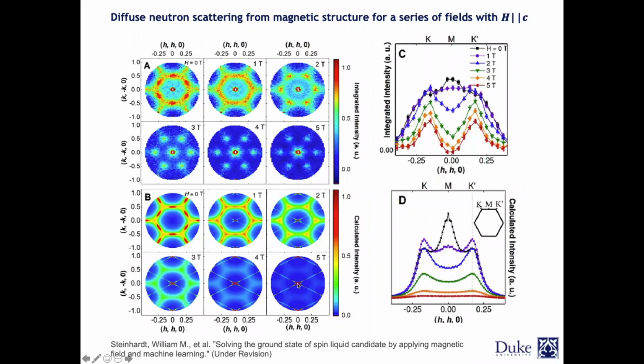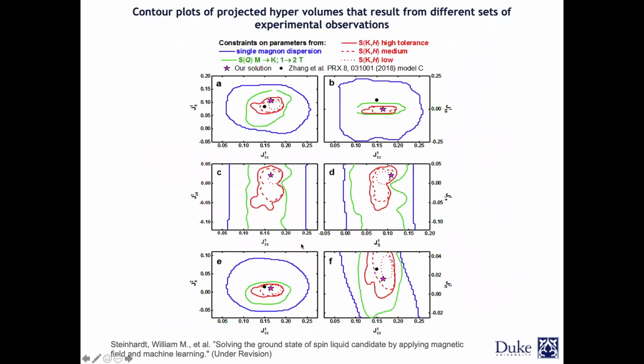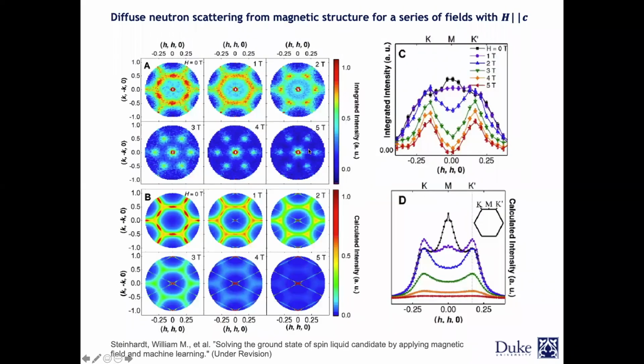Okay, so we decided to do some neutron experiments on this. The key was that we already know that from 0 Tesla to about 5 Tesla in our TDO data, something is happening. Let's go and figure out what is going on. Here, these are the experimental data. The energy is integrated all over, so it goes from almost 0 to about 2-3 meV. All the low energy excitations that are talked about are captured in here and integrated over the area of interest.